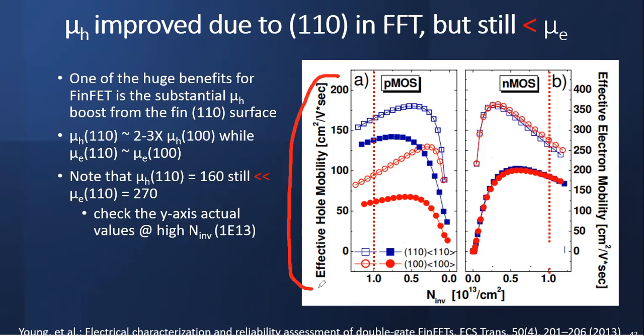Don't be confused. The authors like to change their axis so that they look similar in scale, but they're not. If I check the actual value, at 1E13 per centimeter squared inversion density without doping, here you have 160. And then you look at the electron here, 260, 270. It's still small. This one is smaller than this one because of the scale. So be very careful. Always check the actual y-axis values.